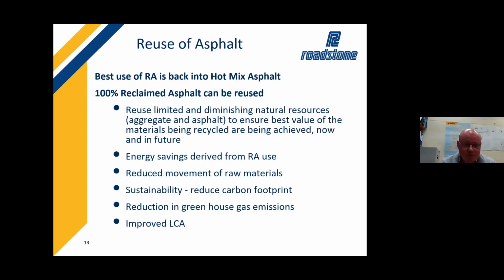Reuse of asphalt is a very important thing that I suppose we're getting to grips with in Ireland. Reclaimed asphalt has its own European standard, I.S. EN 13108 Part 8. It is 100% recyclable back into new hot mix asphalt materials. By recycling or reusing that reclaimed asphalt, you have the savings on the aggregates that would have to be produced, and of course the transport of those, as well as the bitumen that was being used. And so it's a massive part in making our industry more sustainable, achieving a good level of recycling or reuse of these materials in an appropriate manner.